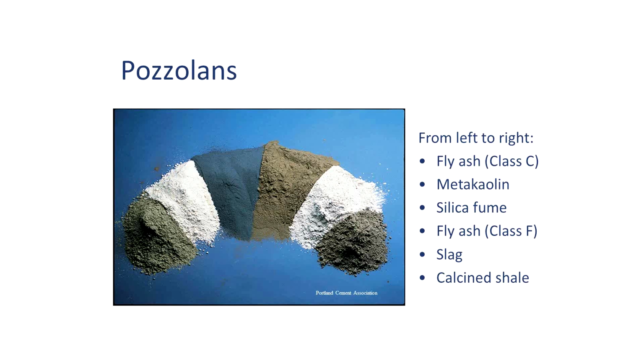Fly ash tends to be sort of a light grayish brown. I've seen fly ash that's almost pale buff. I've also seen fly ash that's almost black. And a lot of the darkness comes from carbon content. Metakaolin is very white. Sometimes it's kind of a creamy pink. After it reacts in the concrete, the color goes away. I've made white concrete with metakaolin that looked kind of pinkish cream, and it looked identical to white cement-based concrete that didn't have any metakaolin in it. So the color of the pozzolan when you're holding it in your hand isn't representative of the color of the pozzolan after it's done reacting.